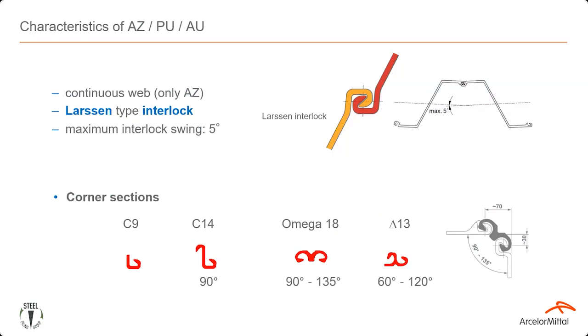Now, with the interlocks, all of our piles have the Larssen interlocks, which means that they can all be connected together. You can also connect a Z pile to a U pile section, and you can also connect to an existing sheet pile wall if the interlock is free and available to interlock. Usually at the interlock, we can achieve 5 degree swing. But if you need tighter corners than those, then we have a couple of corner sections that can help you with those.